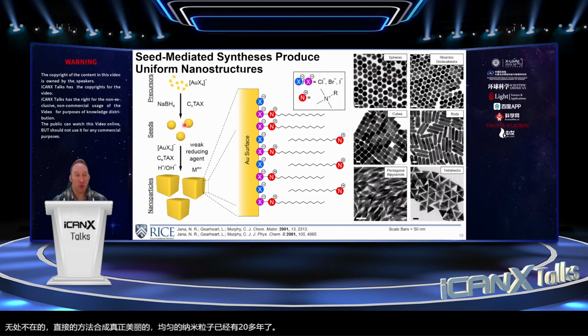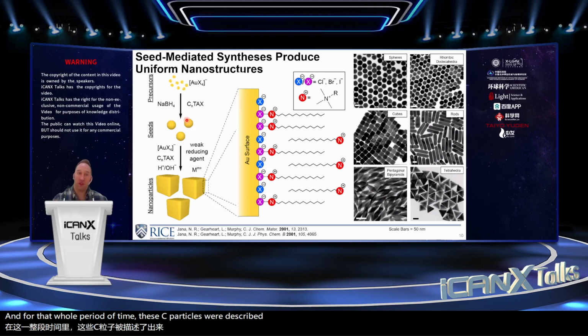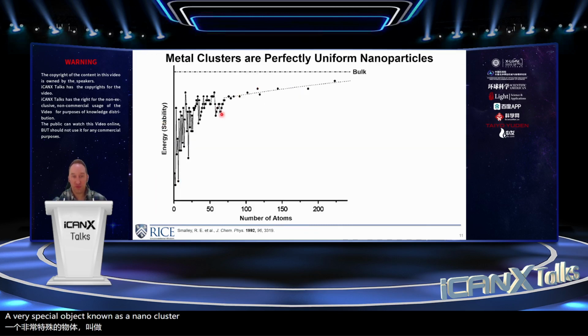And for that whole period of time, these seed particles were described as 3 to 5 nanometer spherical particles. And kind of the amazing, surprising result out of my group is that we think these are actually a very special object known as a nanocluster. So let me be very clear about my distinction between nanoparticle and nanocluster.